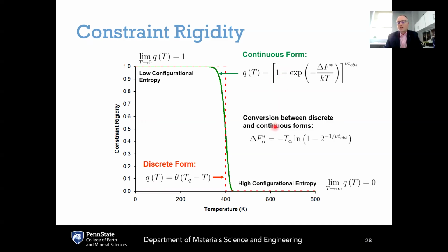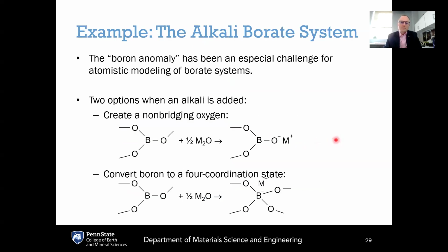And it's straightforward to convert between the discrete and continuous forms if you consider that they both have to pass through 1/2. They both have to pass through 0.5 at the constraint onset temperature. So if you take a constraint onset temperature T_alpha, you can solve for this free energy barrier here, delta F_alpha star. It's just equal to minus T_alpha times the natural log of 1 minus 2 to the power minus 1 over the vibrational frequency nu times the observation time.